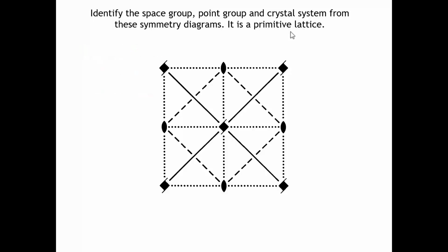Well, what did you get? Can you see the fourfold rotations? Actually, there are 4_2 screws. I would think that's the first thing that comes to my mind. We're looking for generally the highest order rotation axis, because that's going to tell us what sort of space group we have, and that allows us to better interpret the diagrams. And I don't see any sign of a threefold axis. I know now I've got a tetragonal space group. And I also know that I'm looking at the AB projection.